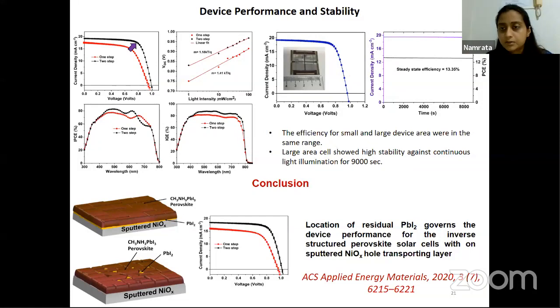using the 1 centimeter square active area. So even though previously with the methyl ammonium chloride vapor treatment and one-step method, we could obtain 15%, but without methyl ammonium chloride vapor treatment, we were still at 9%. So here we have not used any vapor treatment, and we simply compared two-step and one-step method and obtained a higher efficiency for two-step method. So that means there are some defects which are treated by either the methyl ammonium halide vapor treatment or by passivating the surface of nickel oxide.